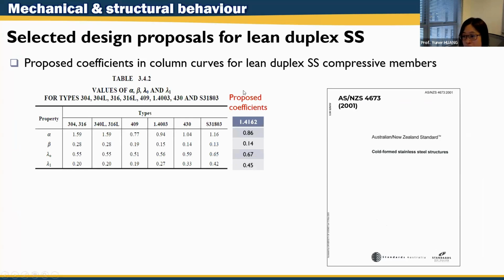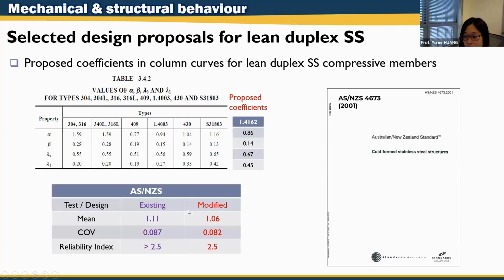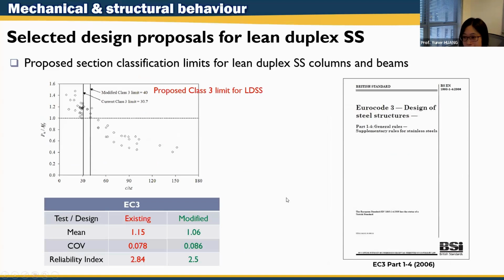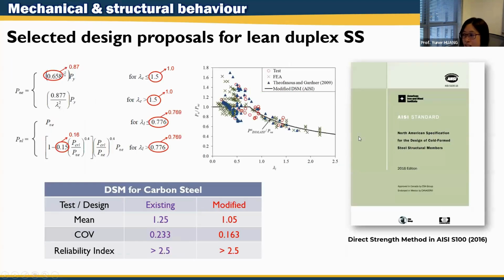So this is our proposed coefficient on top of the Australian standard. And we compare our test-to-design ratio, and we realize our modified proposal provides a less conservative result than the existing one. And we also did the same thing for Eurocode 3 Part 1.4, where we propose a new Class 3 limit for lean duplex stainless steel. And then for the American specification, we proposed new parameters for lean duplex stainless steel in predicting the buckling behavior.